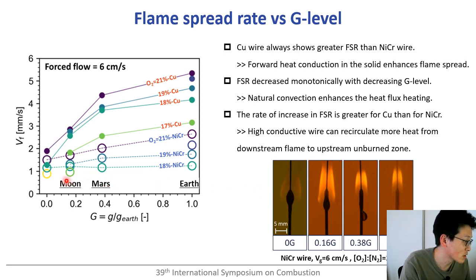Additionally, if we carefully look at the flame spread trend, the rate of increase of flame spread is greater for the copper case than the nichrome case. This is one of the unique features observed for highly conductive wire. Basically, a highly conductive wire can recirculate more heat from the downstream flame to the upstream unburned zone. So the change of heat flux works more effectively to enhance the flame spread of a highly conductive wire. So this characteristic can be associated with flame spread over thermally thick material in high flow velocity conditions.